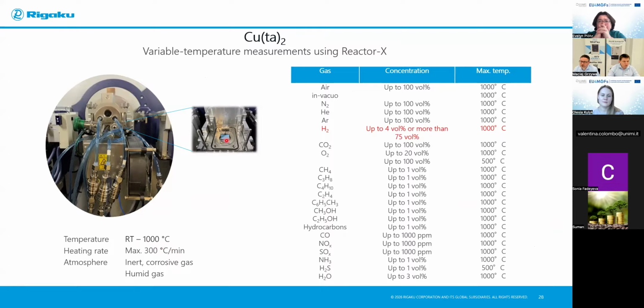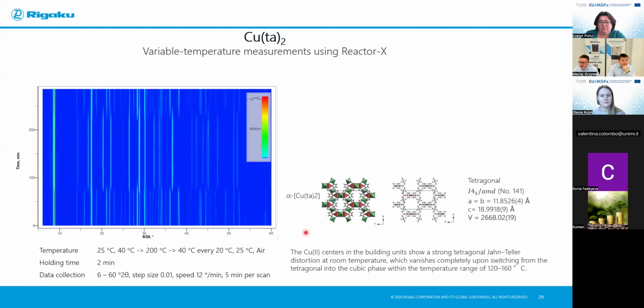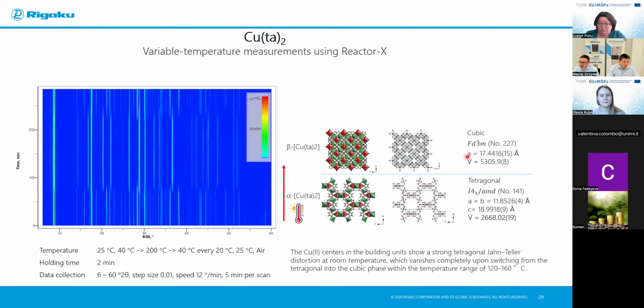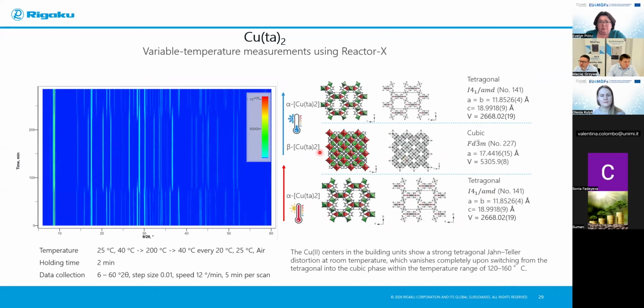The sample is heated by IR radiation from the bottom, and it's possible to use here, of course, inert gas, humid gas, but also corrosive gases like even hydrogen up to 75% volume, and then we can heat the sample to 1000 degrees. And copper triazolate, when it's heated to a temperature higher than 120 degrees, shows a phase transition from tetragonal crystal system to cubic crystal system, and subsequently cooling the sample leads again to the tetragonal phase.